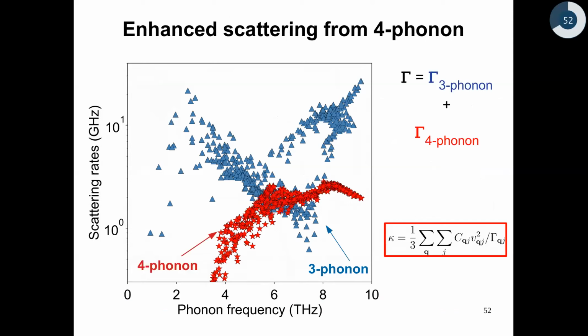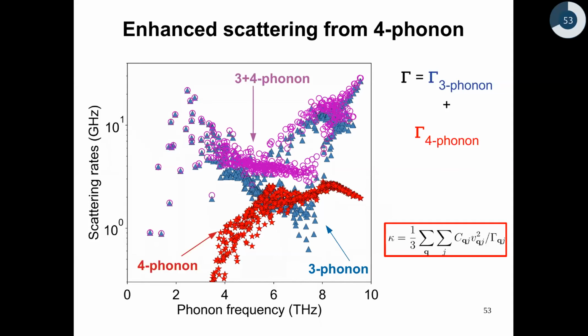Now, if I add the 4 phonon scattering rates to this plot, you can see that 4 phonon scattering rates are the largest precisely in the frequency range where the 3 phonon scattering rates are weakest. So when you add these together through some kind of a Matthiessen's rule approach, you find that there is almost a 10-fold increase in the scattering rates at this lowest scattering rate point. For example, in this region, the blue triangles have been lifted up by a factor of, I think, 4 or 5 or 6 to these purple points.